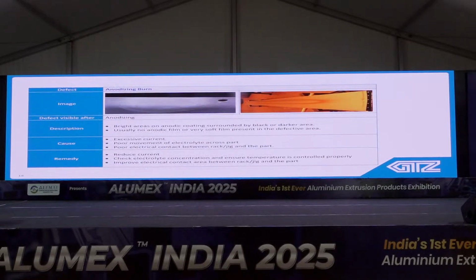Anodizing burn: it is visible after anodizing. This type of round shape pattern in bright anodizing is because of higher current density than normal. Higher current density occurs because of poor movement of electrolyte or poor electrical contact. So current density has to be reduced to get rid of anodic burn, and electrical contact has to be improved.